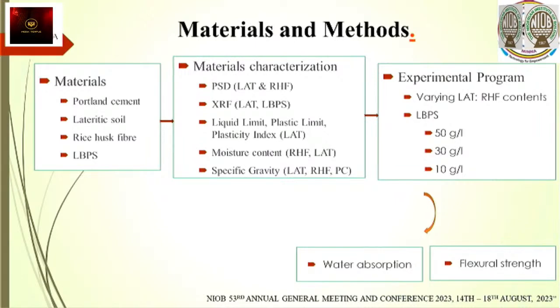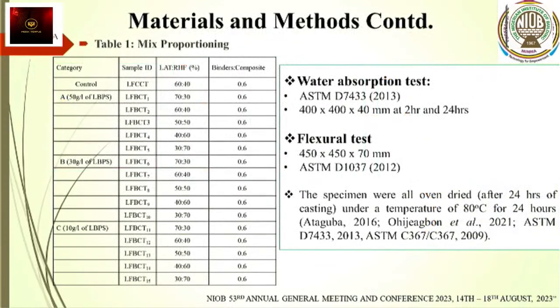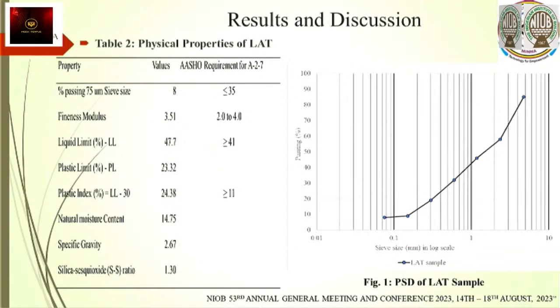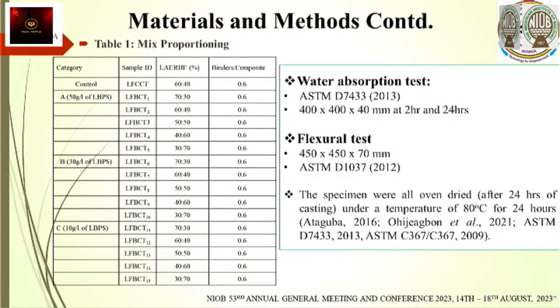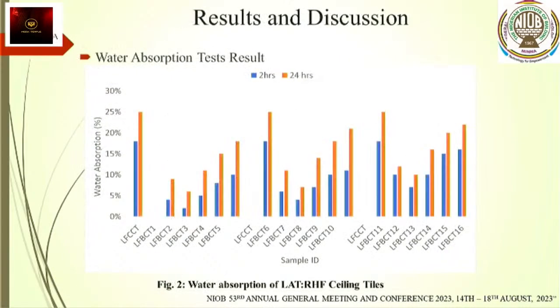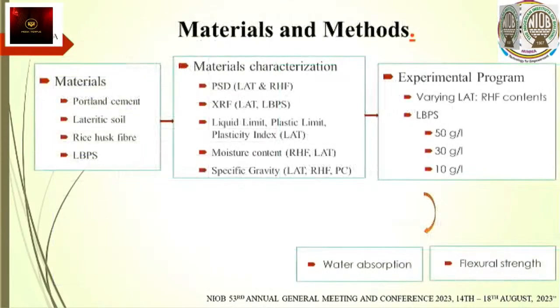The experimental program for the material, we varied the laterite and RHF content from 70-30, that is 70% laterite, 30% RHF. Then we continuously reduce it to up to the time we get to 30-70, which is now 30% laterite, 70% RHF at 10% step intervals. We also made use of the locust bean pod solution at 50 gram per liter, 30 gram per liter, and 10 gram per liter. And the major tests carried out on the tile were the water absorption and the flexural strength.